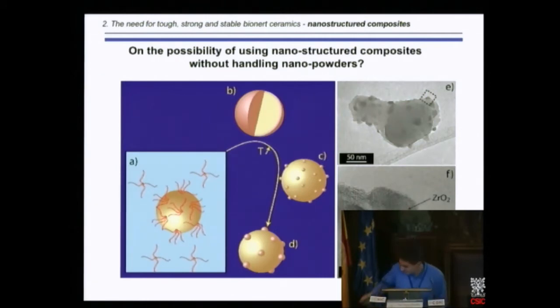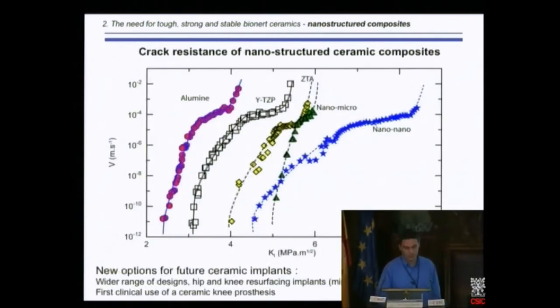And then you obtain something like that, in which you have an alumina grain, in which you have zirconia grains, really nano zirconia grains, which are strongly attached to the alumina powder. So with this kind of strategies, you obtain real materials like that.